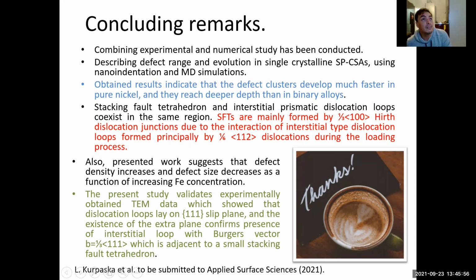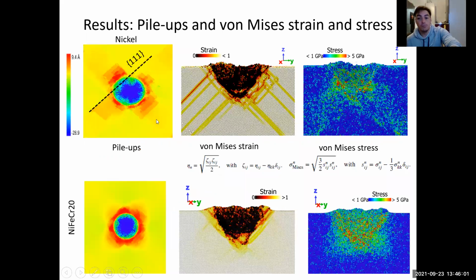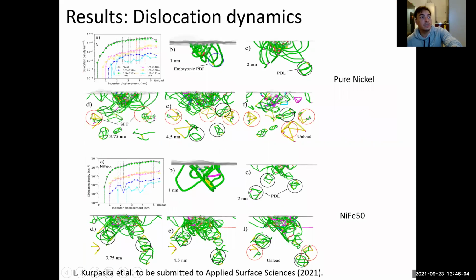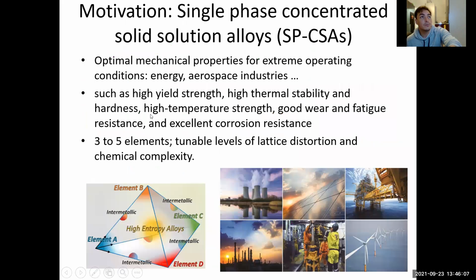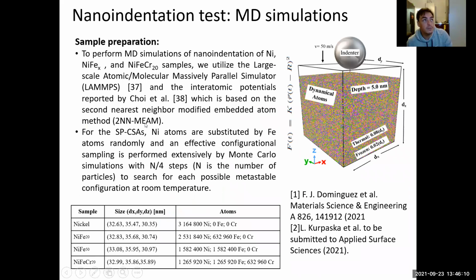I'm using the potential developed by Choi. These potentials are the second nearest neighbor modified MEAM potentials. They are developed by Choi et al. I didn't put the reference, I'm sorry, but they are well tested. Rene and I spent practically 2 months testing the potentials, and everything fits. Okay, very good.